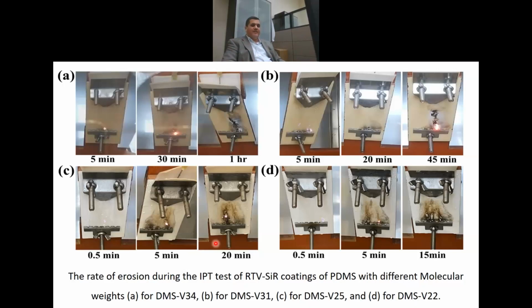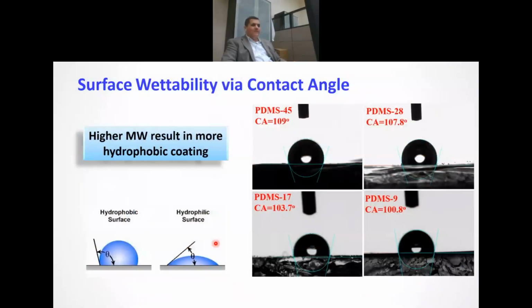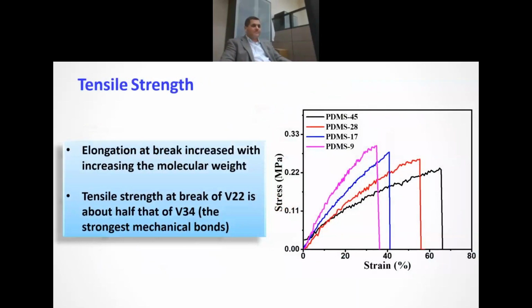So the molecular weight definitely is worth the study, and we have to consider it. We have to take this into account. Of course, we tracked, just to give you an idea, this is the contact angle. The highest molecular weight has the highest contact angle, as expected. So this is all known. But also there is a difference in the contact angle that might eventually affect the IPT and the surface stability or the erosion stability with time.